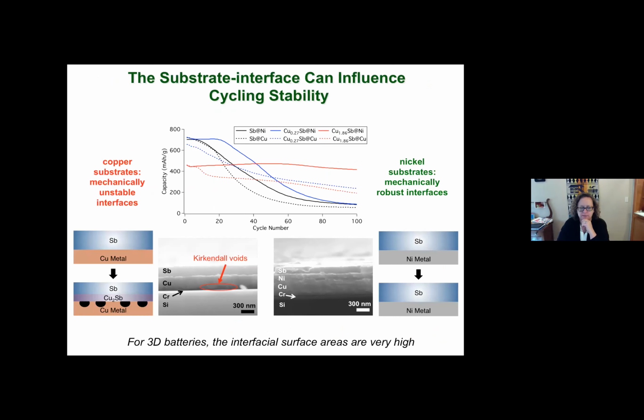One of the key aspects, again, that I think the fundamental research is important for is identifying degradation mechanisms. And I mentioned at the beginning that copper is an anomalously fast diffuser. So on the bottom left, we did an experiment where we were trying to understand why batteries seem to die faster if they were higher in antimony composition versus higher in copper. The copper is there as a conductive framework, but the antimony is the element that actually stores lithium. So ideally you would want a pure antimony electrode.